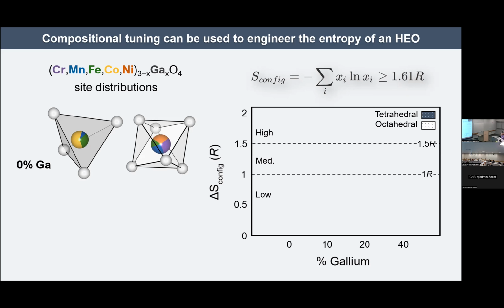And now I can actually experimentally calculate what is my true configurational entropy. It was not accurate in the first place to apply this formula to my spinel because we're generally considering a sublattice configurational entropy. And so I have to treat these 2 sublattices distinctly. And so what do we find? We have less than the high entropy threshold. So the entropy of this starting compound is actually in the low regime for our tetrahedral sublattice, and we're in the medium regime for the octahedral sublattice.